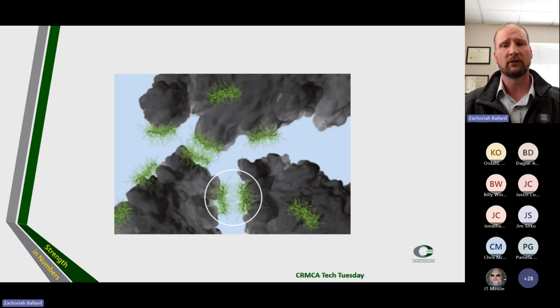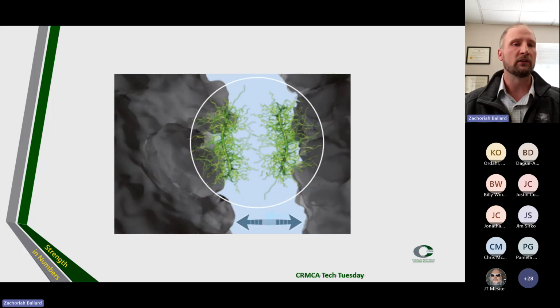It's usually manifested in intermolecular reactions, whereas discussion of steric effects often focuses on intramolecular interactions. Steric hindrance is often exploited for controlled selectivity, such as slowing unwanted side reactions like crystalline growth from cement hydration. And this is a detailed view of improved workability. It's going to push those two particles apart without having to add water into the space between them.